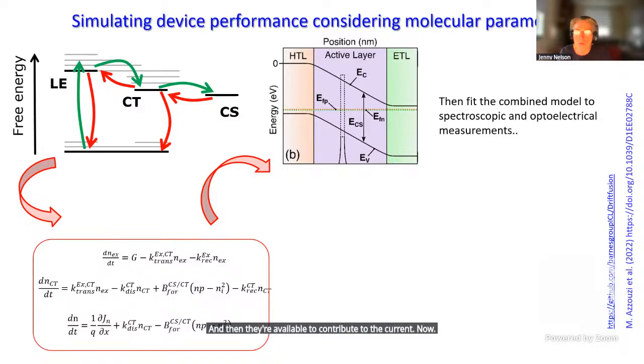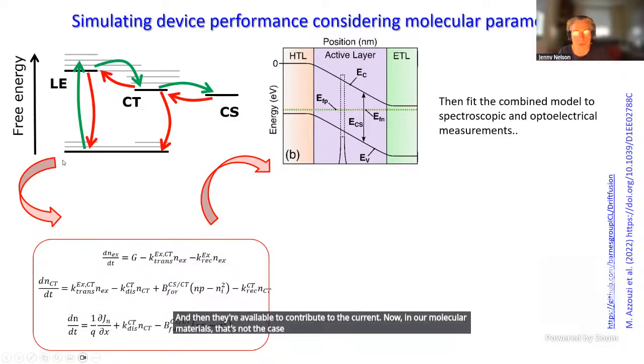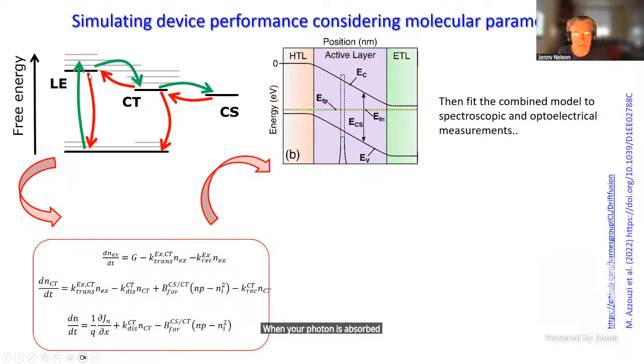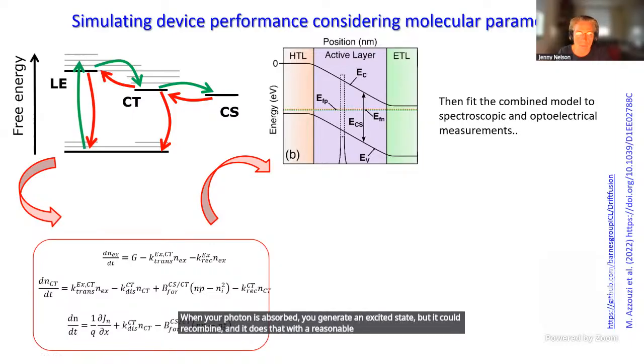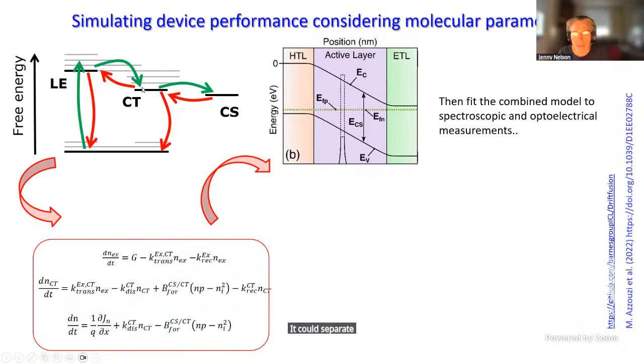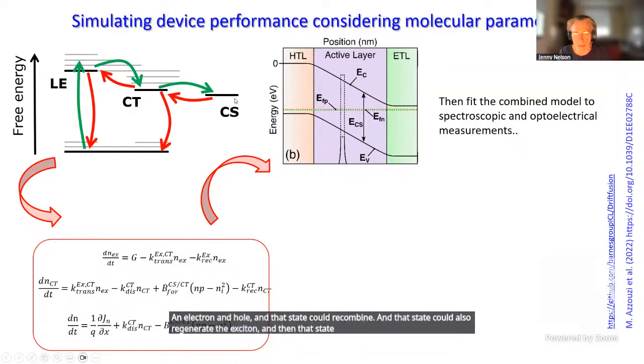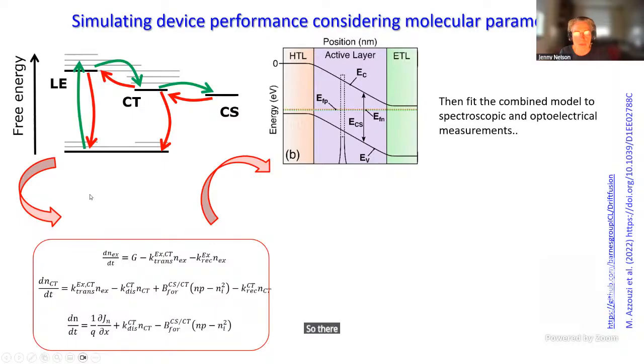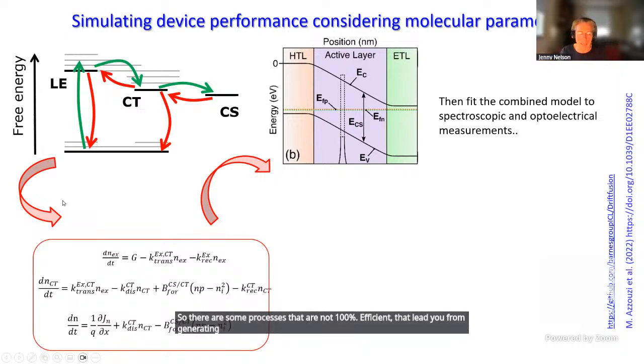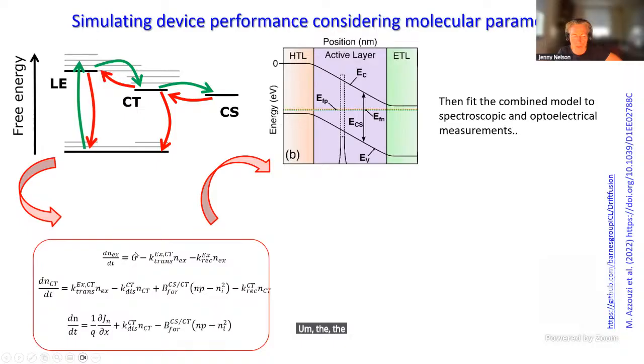Now, in our molecular materials, that's not the case, because when your photon is absorbed, you generate an excited state, but it could recombine, and it does that with a reasonable probability. It could separate into this interfacial state, which is not yet an electron and hole, and that state could recombine. And that state could also regenerate the exciton, and then that state could separate. So there are some processes that are not 100% efficient that lead you from generating the excitation in the material to generating the electrons and holes.